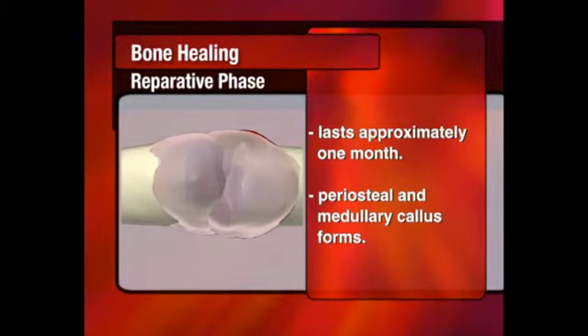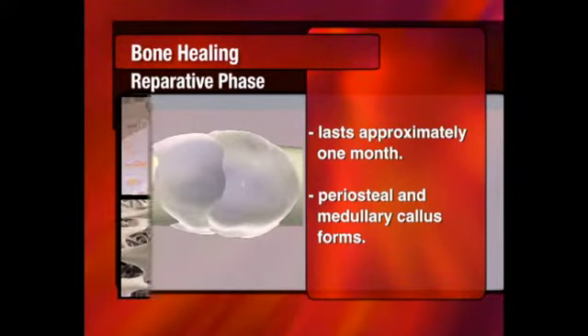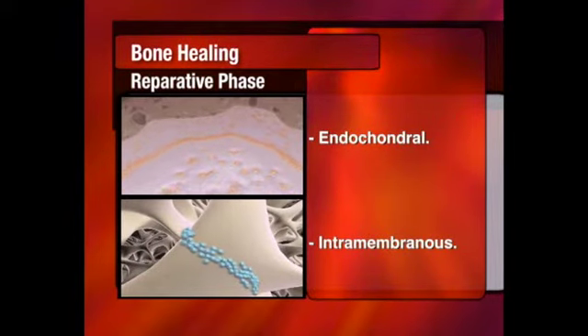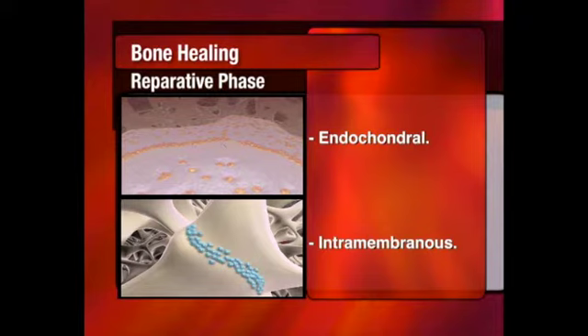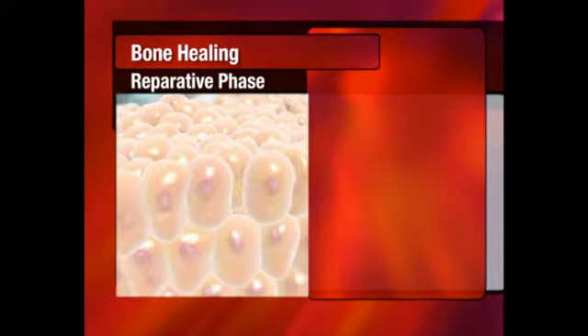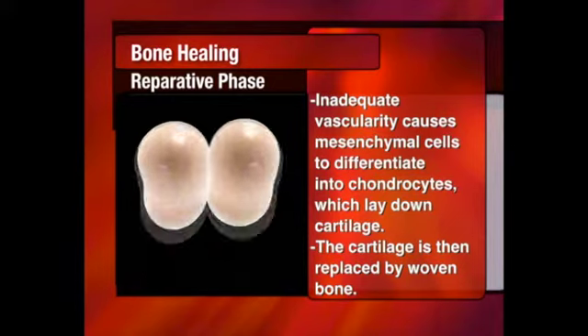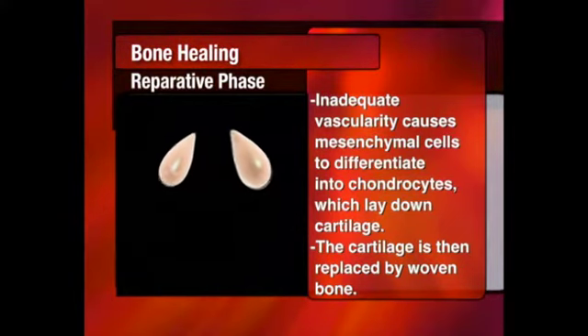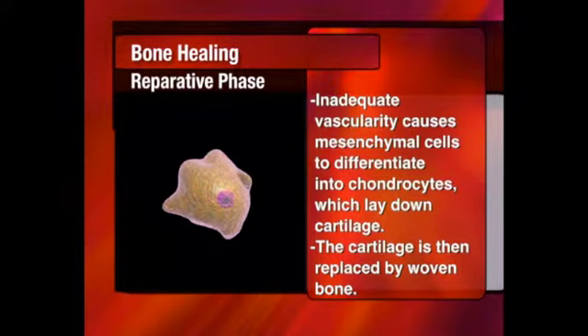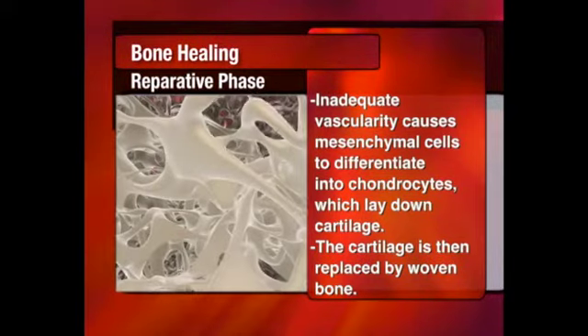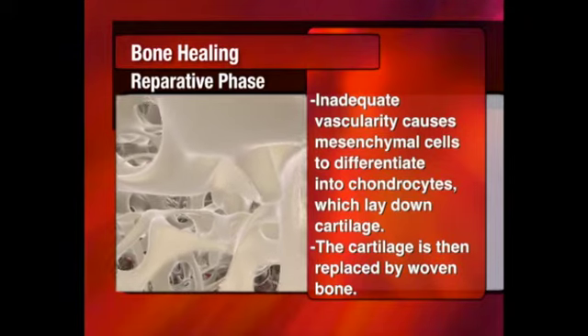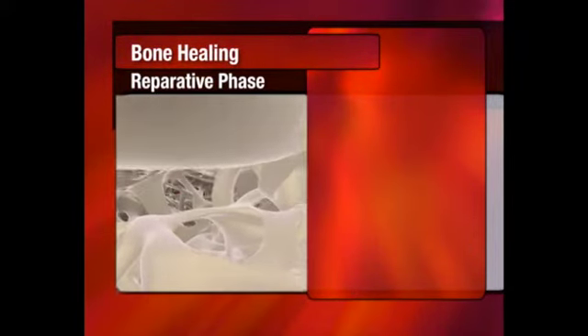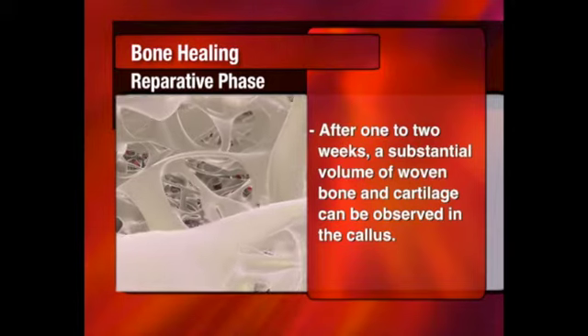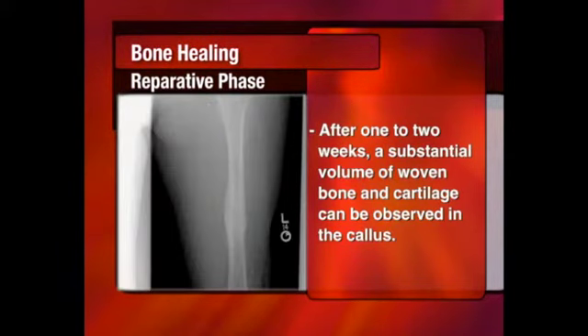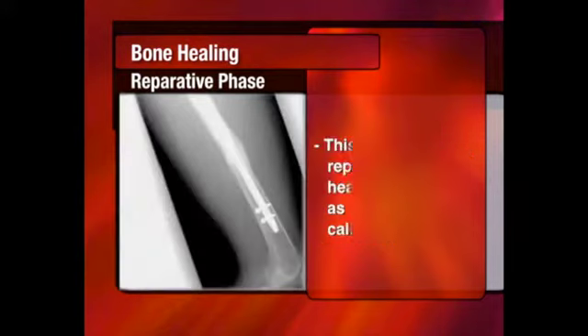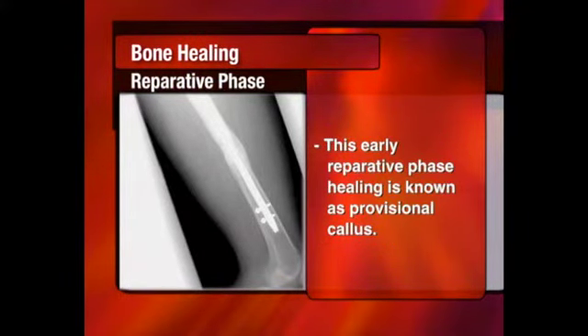During this phase, a periosteal and medullary callus forms. At the site of the fracture, both endochondral and direct, or intramembranous, bone formation occur. If there is inadequate vascularity caused by insufficient immobilization, the mesenchymal cells tend to differentiate into chondrocytes, which lay down cartilage, which is further replaced by woven bone. It takes about 1 to 2 weeks to observe substantial volumes of woven bone and cartilage tissue within the callus. This early reparative phase healing is known as provisional callus.